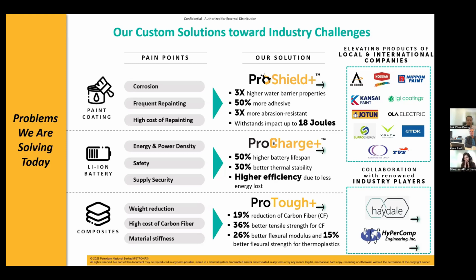Now, with those additional layers of resistance or tortuous paths that we have introduced, we saw improvement in higher water barrier properties. We saw better adhesion qualities, and we also saw better abrasion resistance. And what that really meant was we were now able to extend the service life of our coating. Now, this is perhaps the most advanced solution that we have, ProShield Plus.